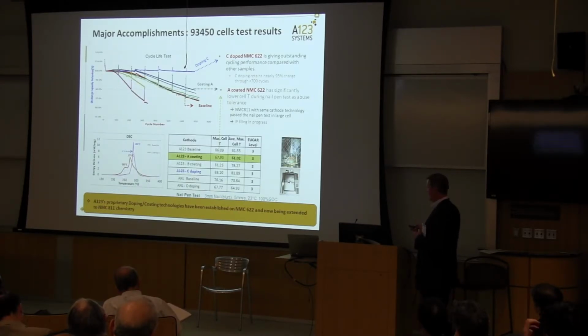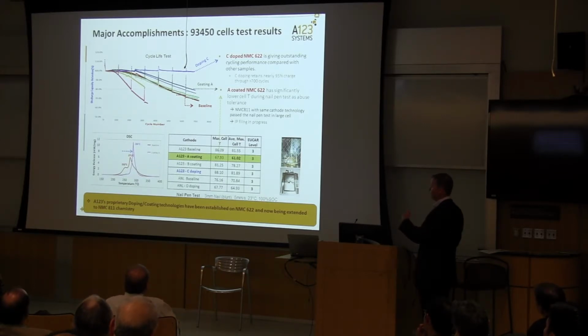So just some initial data. We really look at DSC as well to try to gauge whether we're making some progress. So again, we've developed this in a way using the Advanced Photon Source as well at Argonne to correlate where we start to see the C direction collapse or the formation of the rock salt structure at the surface with what we're seeing from the DSC.